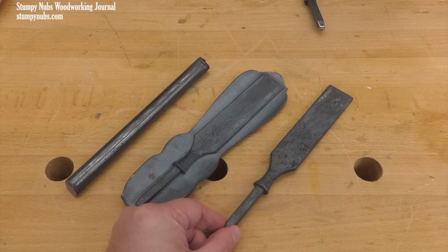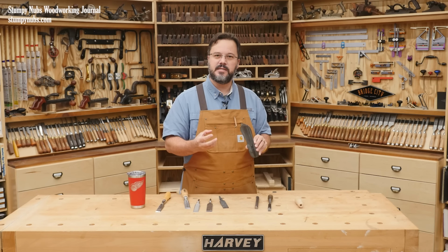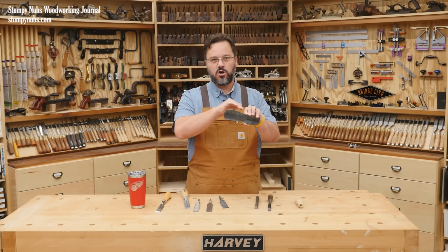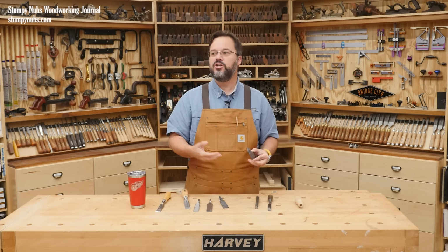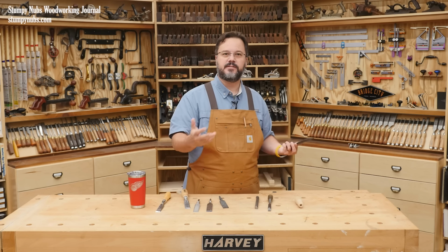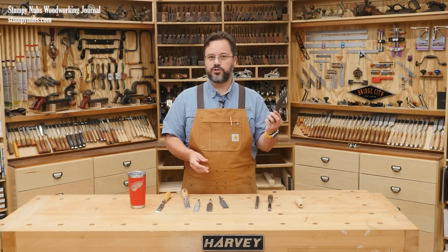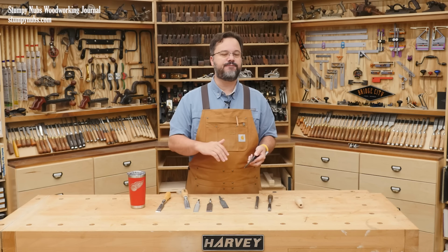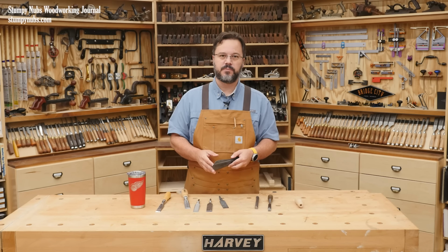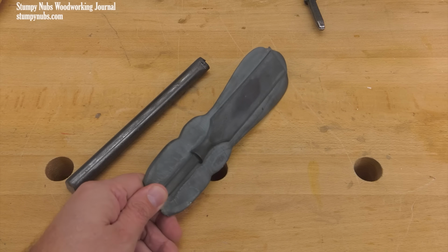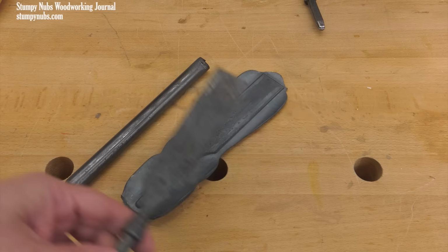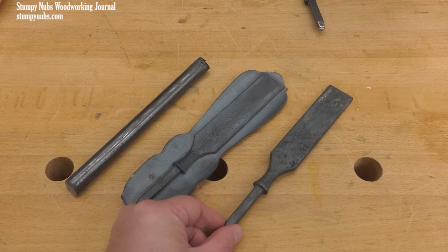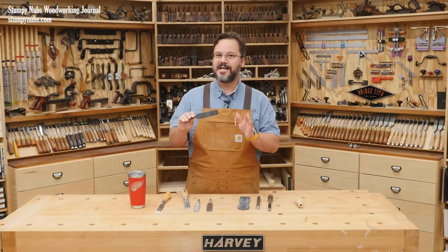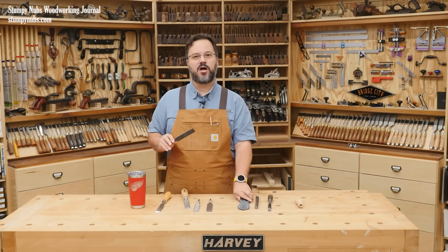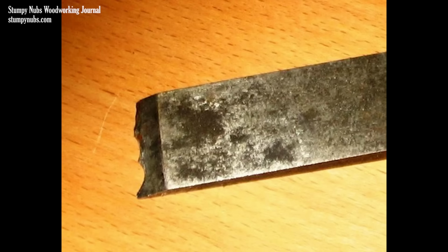Forging eliminates internal voids, it compresses the steel, and it aligns the grain structure along the shape of the tool, which affects its strength, just as the direction of wood grain can affect the strength of a furniture part. Forged tools take a keener edge and they resist dulling far better than other mass-produced tools. Once the steel is heated and hammered into shape, the excess is trimmed off to be recycled, and the blank now looks like a chisel. But it's not ready to sharpen yet. It has to be further hardened, because steel that is soft enough to forge into shape is not hard enough to hold the type of edge that woodworking requires.